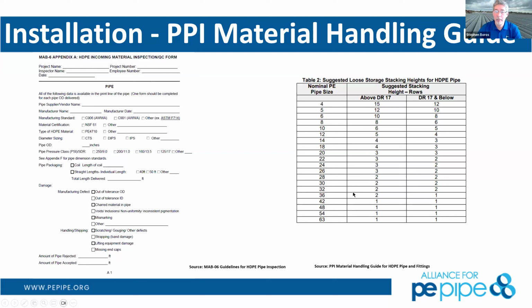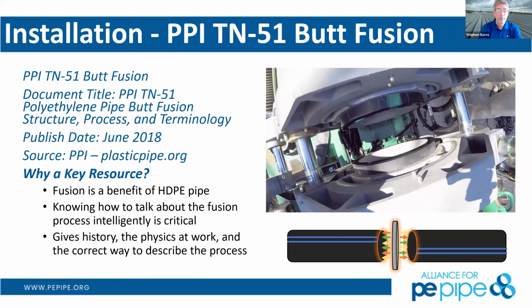Stacking heights as well. Polyethylene pipe, you can stack. The larger diameters, though, it's recommended that you don't stack more than one high. Once you get below 36 inch, you can stack it 2, 3, 4, even 10 high, as long as it's chocked properly and protected properly, or it's not going to fall off and roll over people.